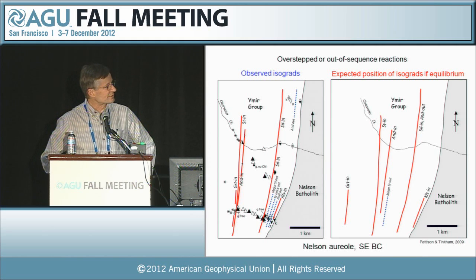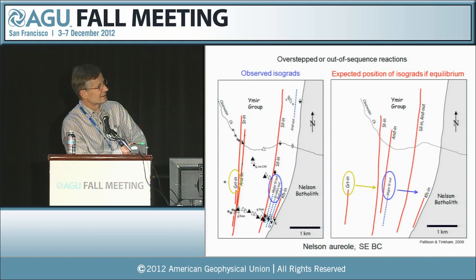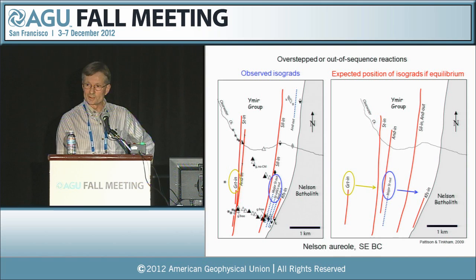Two of the main differences relate to the predicted presence of the garnet zone here, which is in fact absent in the natural setting, and also the predicted disappearance of staurolite, which instead of occurring just a little bit upgrade where andalusite comes in, in reality is observed to occur well upgrade into the sillimanite zone. So again, this would be an example of, in one case, an overstepped, and in the other case, an out-of-sequence reaction.